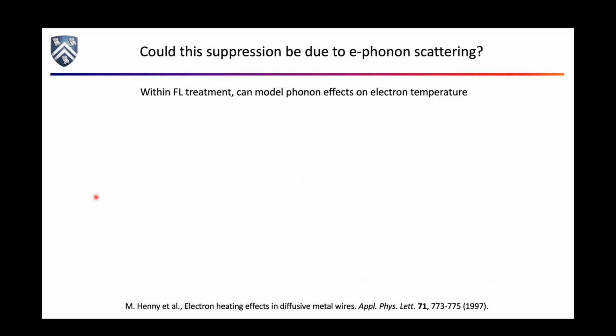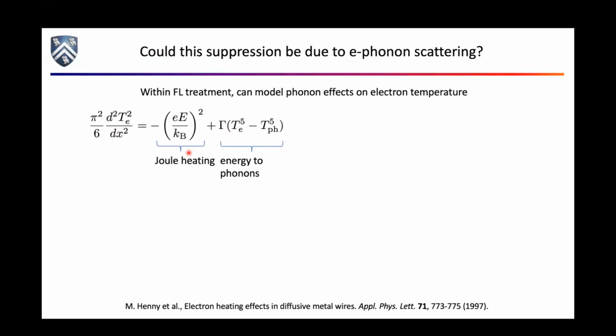So maybe it's phonons. Maybe somehow phonons are suppressing the noise, because I told you that's a possibility, right? Within the Fermi liquid treatment, it's possible to model phonons, right? What you can do is, this implicitly assumes the Wiedemann-Franz law, but you can basically say, okay, I'm going to let the electrons trade energy with each other, and they're going to thermally conduct heat out the ends of the wire, and I'm going to let them lose energy. There's some local electronic temperature, and I'm going to let them lose energy to the phonons, right? And let's assume the phonons are cold. So you can model this thing. This all works nicely, basically.